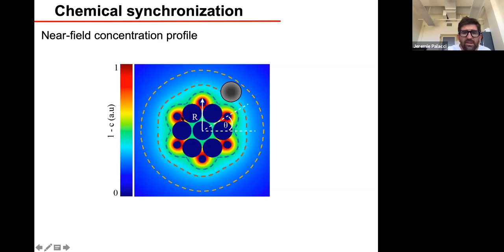And so what we see is that obviously we have a sink of hydrogen peroxide near the hematite. And in the far field, thanks to Gauss theorem, we recover an isotropic concentration profile. But in the near field, we see that our concentration profile is getting the hexapolar symmetry of the microgears.